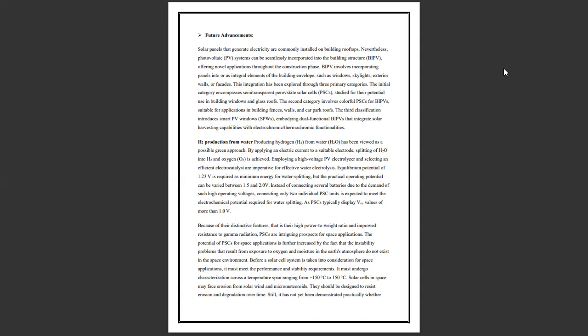Instead of connecting several batteries due to the demand of such high operating voltages, connecting two individual PSC units is expected to meet the electrochemical potential required for water splitting, as PSCs typically display open circuit voltage values of more than 1.0 volts. Because of the distinctive features, which are their high power to weight ratio and improved resistance to gamma radiations, perovskite solar cells are intriguing prospects for space applications.